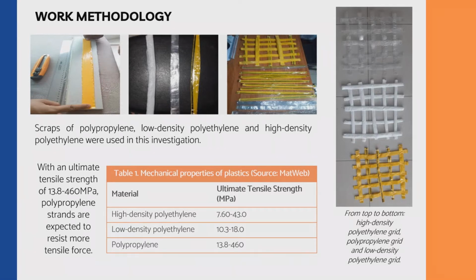Work methodology. Scraps and pieces of polypropylene, low-density polyethylene, and high-density polyethylene were used in this investigation. Two geogrids were made from each type of plastic as prototypes. Table 1 shows the ultimate tensile strength of each material. With an ultimate tensile strength of 13.8 to 460 megapascals, polypropylene strands are expected to resist more tensile force.